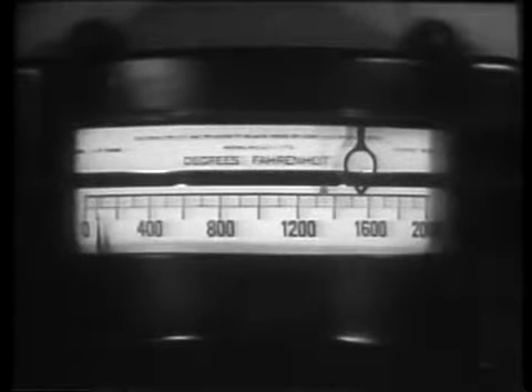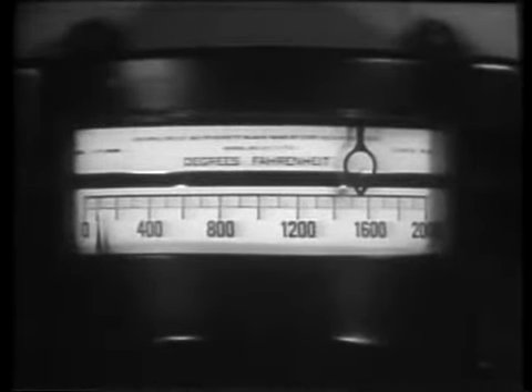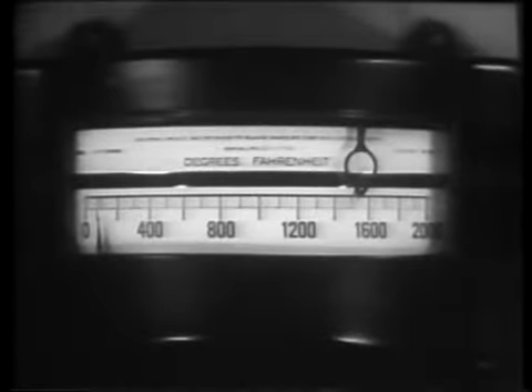In full annealing, parts such as these, made of plain carbon steel, are heated slowly to about 75 degrees Fahrenheit above their upper critical temperatures. In this case, 1,525 degrees. To assure an even temperature throughout the piece, it must be held at the proper annealing temperature for about 1 hour per inch of thickness. Then the heat is shut off, and the material is allowed to cool slowly in the closed furnace.